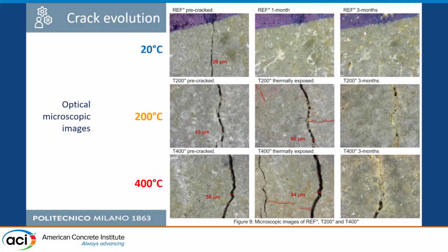Here there is a visual interpretation of what is happening. First row 20 degrees C, second row 200 degrees C, so after thermal treatment, and the last row 400 degrees C. You see what happened in time. This is after thermal treatment. 20 degrees C, there is no thermal treatment. Then after 1 month and after 3 months, you see that you have the closure of the crack. And this is what is possible to see via digital microscope.